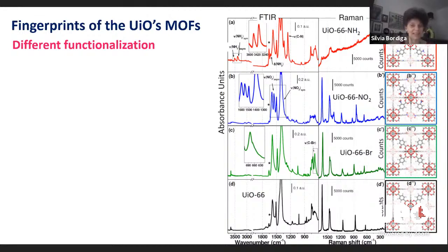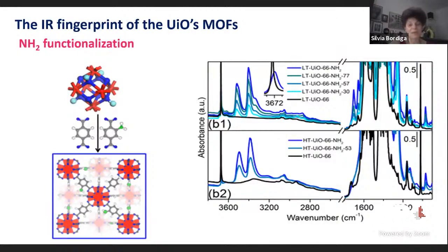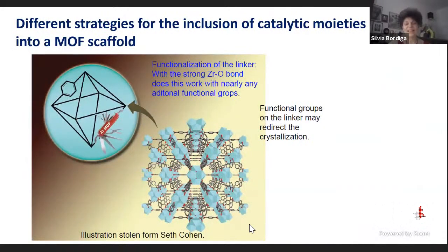We can make these materials having all the linkers functionalized with the extra atoms, or for instance, we can play with mixed linkers. And in this respect, we can follow some fingerprint of the material, in this case the NH vibration, and we observe the possibility to monitor the level of exchange of the linker by monitoring the increase of the vibrational property of the NH, which are substituting in the linker, as reported here.